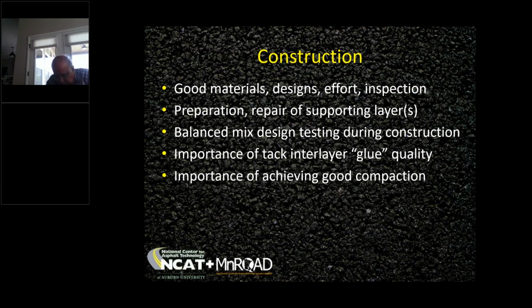The importance of achieving good compaction. We have a couple different experiments on the track. One focused on what happens to performance when density goes from a target of 94% all the way down to 88%, at different levels in between. And then we've got one that FHWA has funded, on what happens when we achieve a higher level of compaction than the typical 94% DOT target. So we've done research. We know that higher levels of density produce better performance, and we're working now to quantify what happens when a DOT makes a decision to accept the job based on lower density.